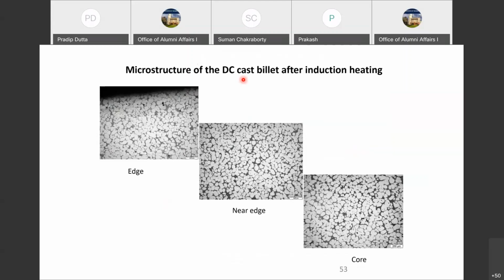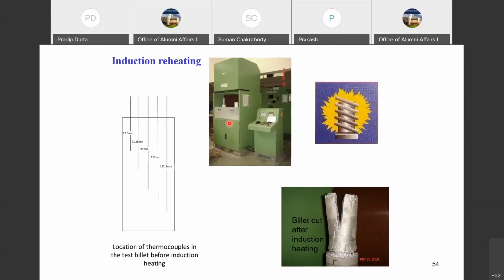After induction heating, we see that everywhere, whether at the core or at the edge, we get the non-dendritic microstructure. So now we are in a position to reheat this to the semi-solid temperature, using induction heating. Here also we have done modeling of this induction heating process to arrive at the temperature distribution inside the billet, and then finally choose the right kind of heating mode so that we get near uniform temperature before we put this into the die casting machine.